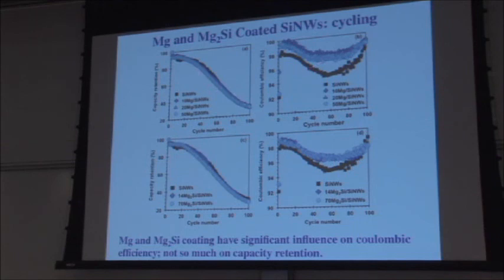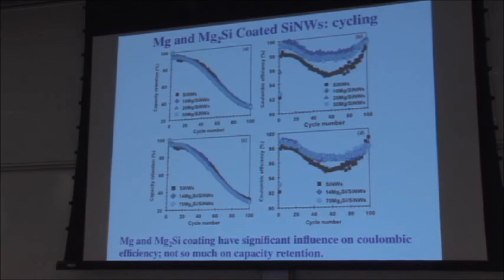So zero improvement in the capacity retention, literally negligible, nothing, but a pretty significant improvement in the Coulombic efficiency, which is, again, what I said before, a secondary but just as important issue: how do you keep from sucking up all the lithium in a real battery. And you have quite a boost in the Coulombic efficiency, especially when you're using pure magnesium coatings. And it actually doesn't really seem to matter how thick the coating is. So these are all essentially the same curve, right? It's kind of a thick curve. And here's the pure silicon nanowires by itself. And again, interesting, your Coulombic efficiency goes up once you start getting significant levels of failure happening.